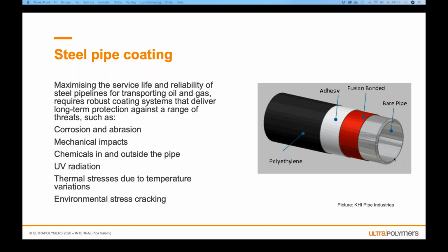So when you pump oil or gas from the North Sea to land, they use steel pipe, but due to the corrosion, they have to coat it with polyethylene. The steel pipe has fantastic mechanical properties, but it's even better now when they coat it with polyethylene. So it's good chemical resistance outside the PP pipe, sorry, and UV radiation during storage.